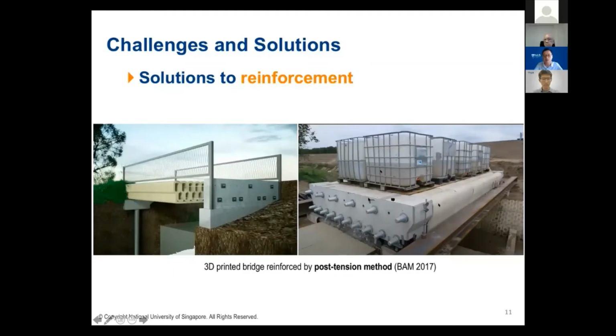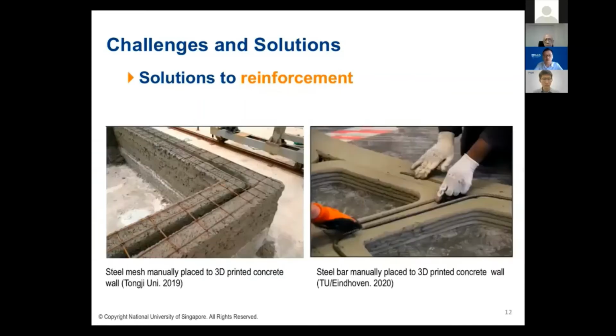And this is how they did the preloading testing. Now this bridge has been in use for 2 years. I think the condition is very good now. This is the post-tensioning from the Netherlands. And some research groups manually put the steel mesh or steel bar during the printing. So the previous one was after printing, and in this one, they are adding steel mesh or rebar during the printing. So after they print one layer, they will put some steel mesh or steel bar manually. So the shear strength can be obviously improved.